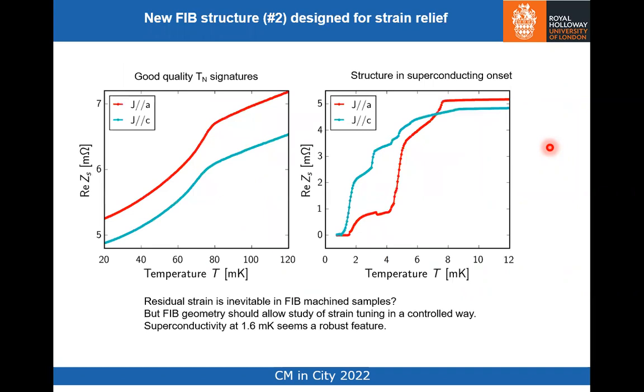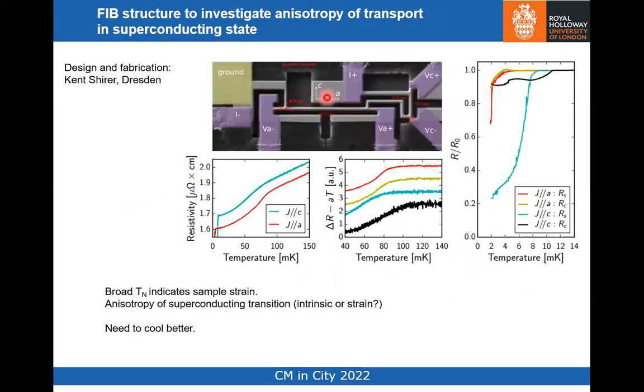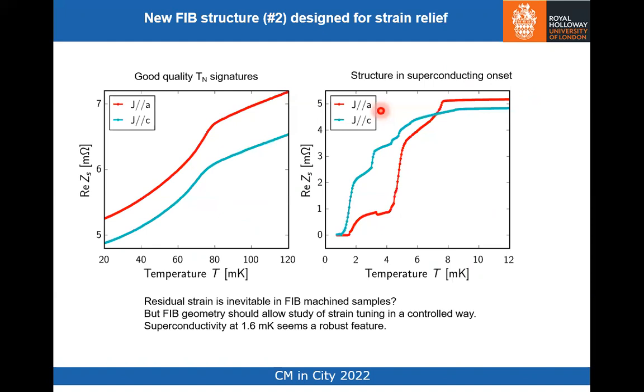So even when Kent Shirer worked extremely hard to make a new FIB structure that was designed for strain relief, what you see is, so it's a wire. I should have explained this. So here's an example of a wire. There's the C-axis, there's the A-axis, and there's current. We can probe different sections of this. So we can probe this bit here where the transport is along the C-axis, and then we can probe this bit here where the transport is along the A-axis.